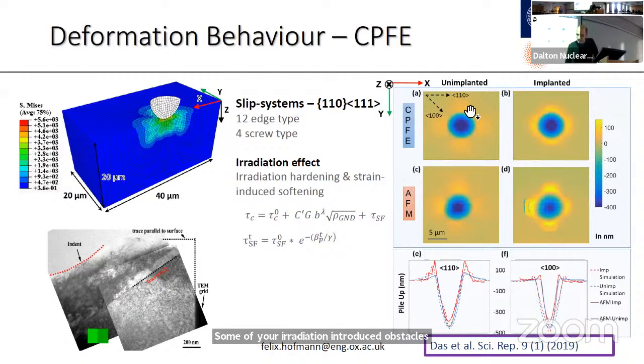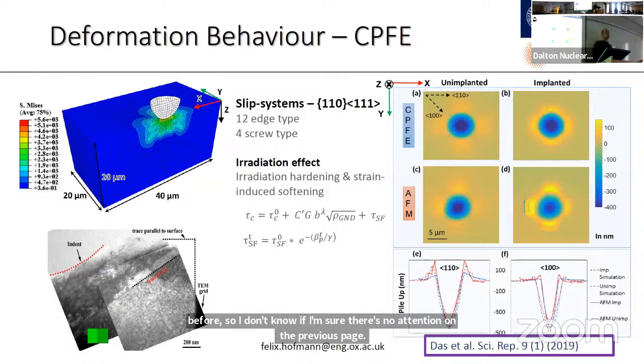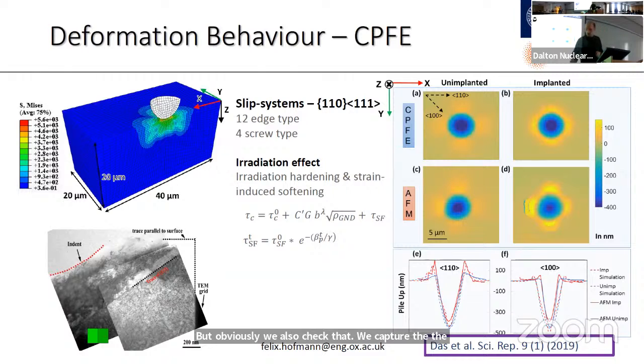So this here is the prediction from crystal plasticity. Down here are experimental maps of the surface topography from AFM, and you can see that this matches quite well. We also capture the four-fold symmetry that you have because of crystallography. Obviously, we also check that we capture the low displacement behavior well.